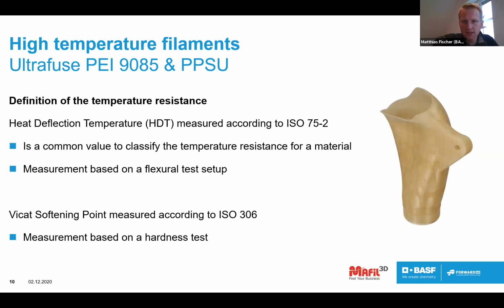In general, when we talk about high temperature products, we should first make the definition of the temperature resistance. We usually do it with 2 methods. It can be either the heat deflection temperature, which is a special measurement method to see how stiff a material is with an increase in temperature. But it can also be the so-called Vicat softening point according to ISO 306, which is based on a hardness test. But in our case, it's not so common. We usually use the HDT value, which is also nice for engineers, because with this value we can at least estimate how the stiffness of a part will drop at a certain temperature.